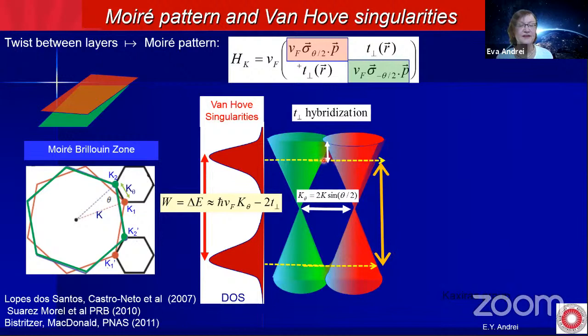So a saddle point in the band structure translates into a divergence in the density of states, or a large peak in the density of states, and this is what we call Van Hove singularities. Now, the distance between these Van Hove singularities was the original energy difference between the intersection of the cones, minus the hybridization energy.